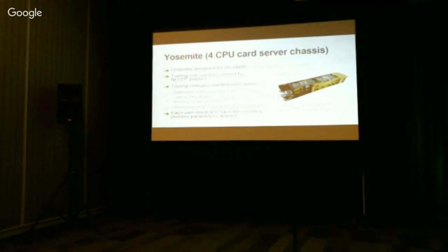So here's a picture of Yosemite. This is the first cubby-based sled that we've done, which uses only the natural fiber-filled polypro for all plastics. We don't use any other plastics in it. And what's interesting to note about this is that it was originally designed for PCABS. When the original design was done, we hadn't qualified the material yet. However, we were able to go back to the original tooling, and with some very minor tooling modifications, adding some thin ribs in a few places to improve stiffness, for instance, we were able to use the old tooling without any other drama. But one thing that you do need to keep in mind is that the processing for the polypro material is definitely very different from PCABS.